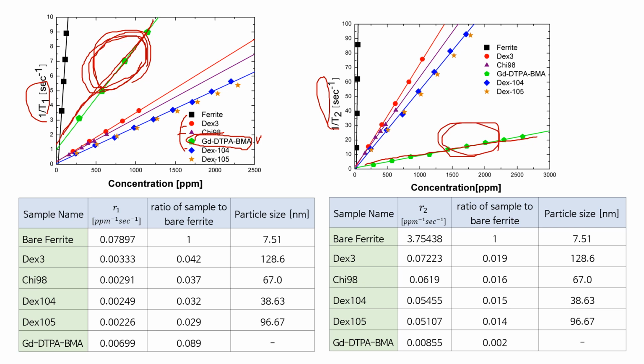for the Gd-DTPA. So Gd-DTPA is a T1 contrast agent. And the others are ferrite nanoparticle contrast agents. And for these ferrite nanoparticle contrast agents, T2 relaxivity is much larger than T1 relaxivity. So these nanoparticle contrast agents can be used as T2 contrast agents.